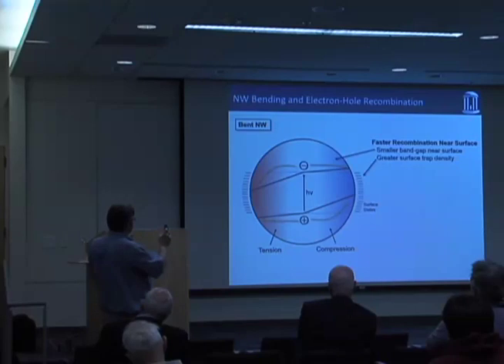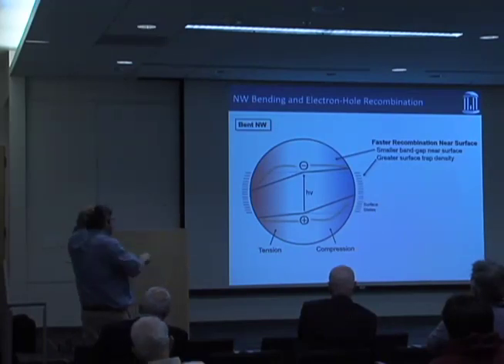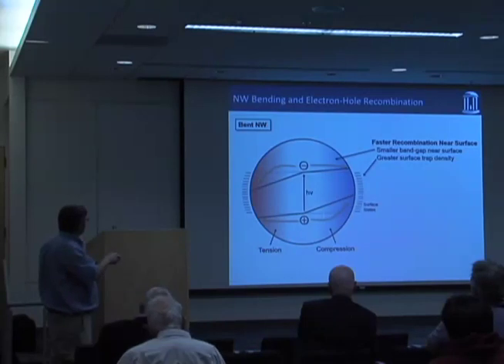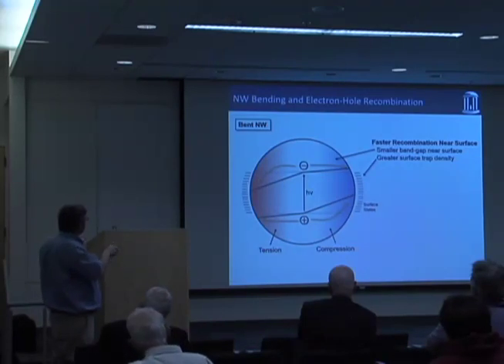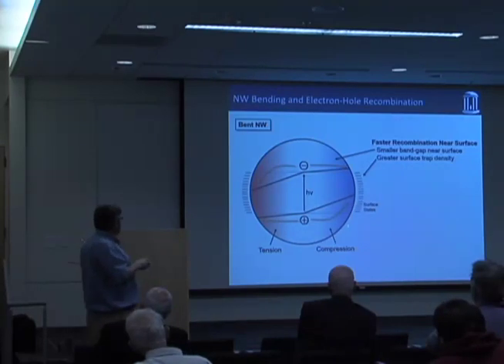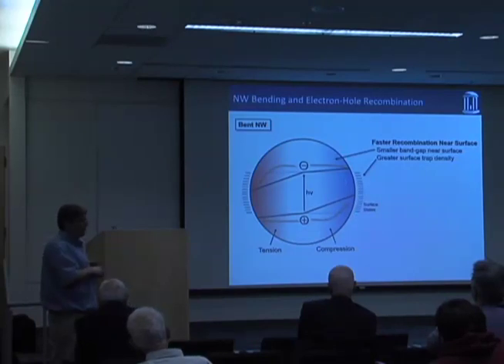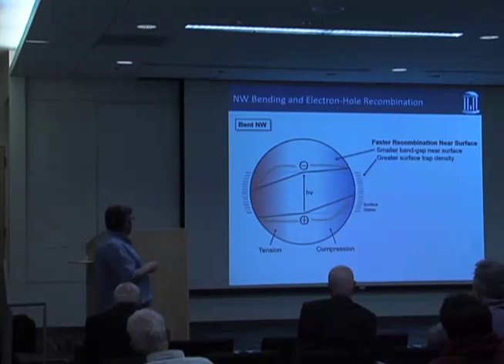But then as I bent it, you can imagine the wire is coming out and curving off that way. On one side of the wire, I'm going to be under compression. On the other side, I'm going to be under tension, and the bands are all going to shift. And so maybe we're introducing more surface states here, but maybe we're also just seeing an effect of the change in electronic structure near the surface. And so we're trying to figure out.